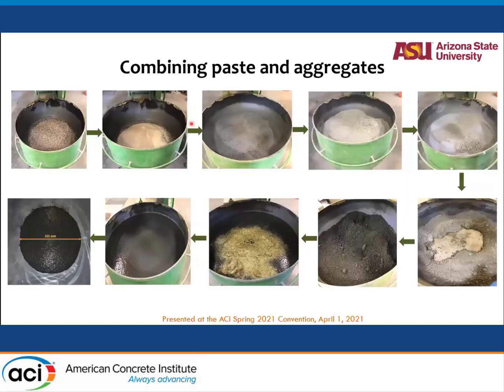Now you combine paste and aggregates. Again, we had to do it through a sequential approach. So the aggregates were blended first with sand, and then we put in silica fume into that so that aggregate shearing will break whatever lumps of silica fume are available and make sure that silica fume is well dispersed. The other binder materials go in next. So all the other binding materials, silica fume, cement, all of them, they're mixed with some amount of water, typically a third of the mixing water. So you get like that. Then you add the remaining water in a couple of more steps.